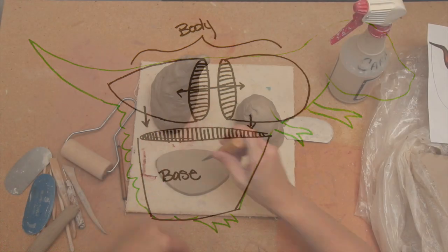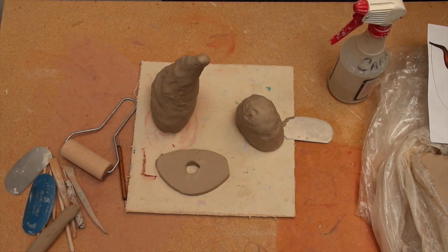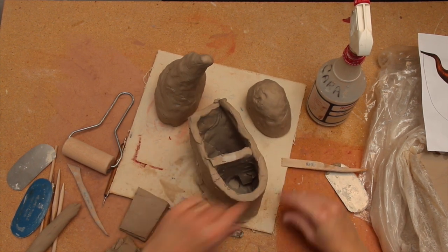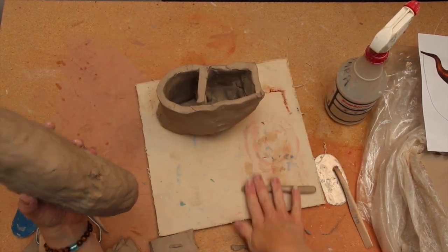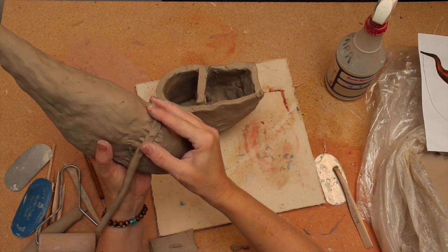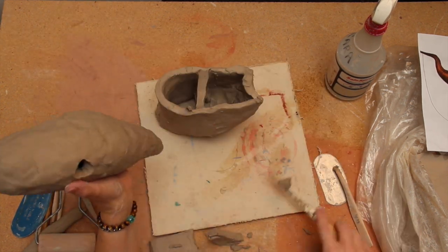After that fun first sketch is completed, have your students complete one more sketch. This should be a simple breakdown of shapes that can be pinched and arranged into a general form before the details are added. When the students are ready to build the basic form, have them score and slip each pinched element together carefully. Remind them that an internal support system will allow for faster building and a stronger piece while they work. It's pertinent that you monitor the students' progress and remind them to have a system of holes within the piece to release trapped air. Any part that is sealed off and contains air will explode in the kiln.